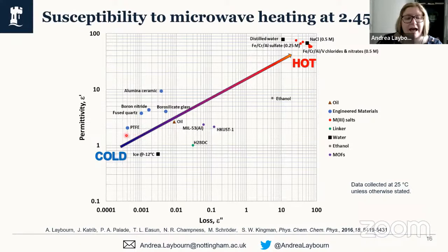So we can see that if you have a low dielectric constant and a low dielectric loss, then you're going to be in a situation where you would expect your reagents to be cold. Whereas if you have a high dielectric constant and a high dielectric loss, then you would expect your materials to heat very rapidly within the microwave field. And we can see that for the example of the MOF reagents, we've got the metal salts, and these are up with salty water and water itself up in this region. So these will get very, very hot. Ethanol will also heat very well in a microwave field.